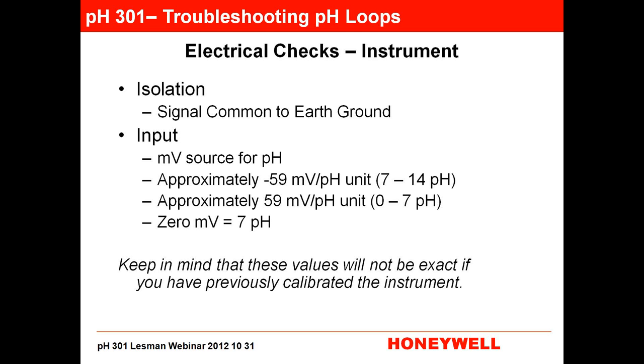You can also do an electrical check for the input. If you have something that will generate millivolts, then you can actually put in millivolt values, disconnect the pH sensor, connect up the millivolt source, and generate millivolt values and drive it to specific pHs. You can also do those tests inside most modern instruments, like our UDA2182. If you go into the maintenance screen, you can pull up some test values where you can test it to see how the input's working and how the output is working.